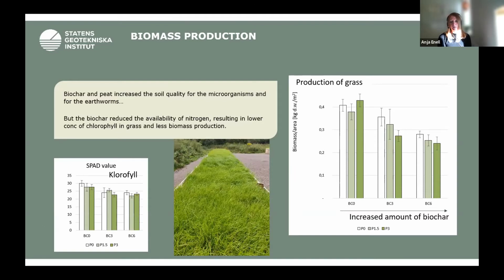And low availability of nitrogen also resulted in lower concentration of chlorophyll in the grass and less biomass production. And this is only after one growth season. And now when we are doing a follow-up study, we can see that it has been evened out. So now, 2 years later, it looks like the biochar is again releasing nitrogen.